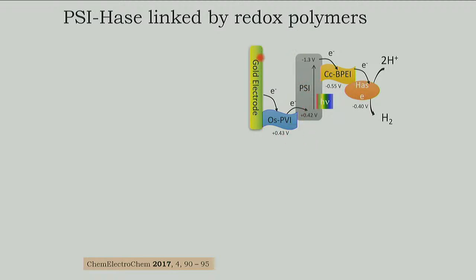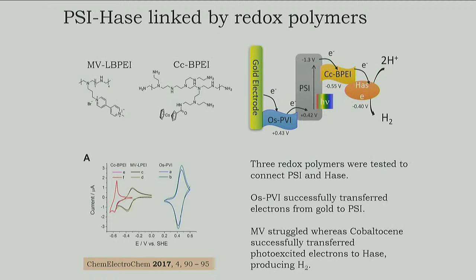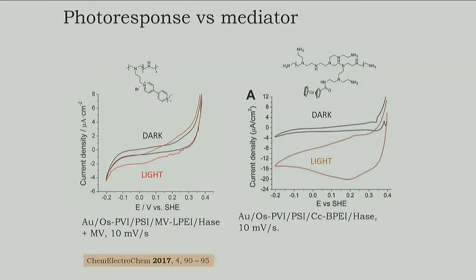So we developed this system here with an electrode modified with an osmium polymer that is going to transfer the electrons to the photosystem 1 that are pumped with the light here, and to a secondary polymer that goes to the enzyme, and the enzyme is producing hydrogen. We tested here two polymers, one with a methyl viologen derivative here, and another one with cobaltocene. Here are the redox potentials. We can see this is the osmium polymer, this one here, and these two. We were comparing which one is going to connect better with hydrogenase. And of course, we found that the cobaltocene one was responding much better.